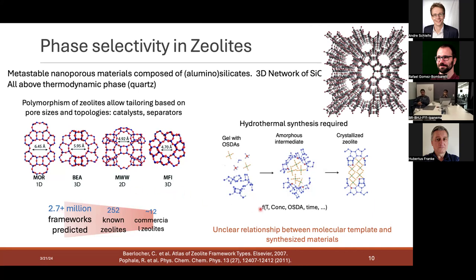And they're made hydrothermally, both in the lab and at scale. Fortunately, these things are made in very similar ways in the lab and at scale in batch reactors, where you essentially put the inorganic precursors, control time, control concentration, and over the space of a week or two in what's essentially a pressure cooker, the precursors form into a gel, and out of the gel crystallizes a solid. And then there's a secret ingredient, which is the use of molecules such that the inorganic piece crystallizes around the pore and around the molecule.